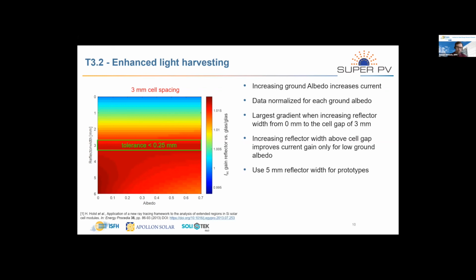And then this light is lost because it is absorbed by the absorber. So ideally, if you want to have a module that is applicable for a wide variety of ground albedos, you want to stay in this region. And then you also have to consider positioning tolerances or manufacturing tolerances of your PV module, which were given here by our industrial partners to be 0.25 millimeters. But in the project, we also figured out that it is very dependent on the printing technique, since it very much depends on the manufacturer of your colored glasses. They also have a good variety in the positioning and also the width of your geometry of the white reflector. So in the end, we decided to go for 5 millimeter reflectors in our prototypes.